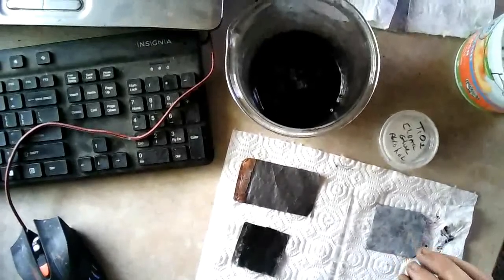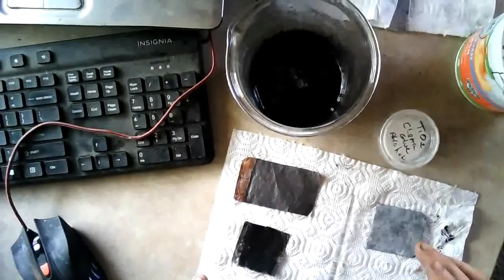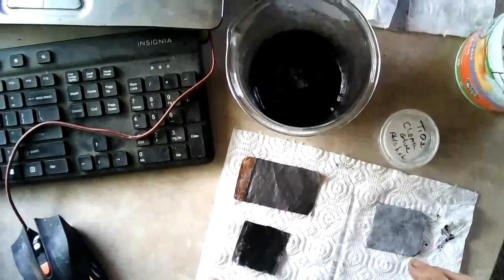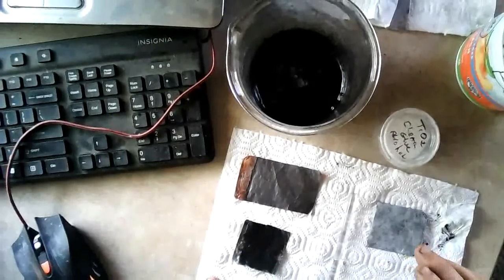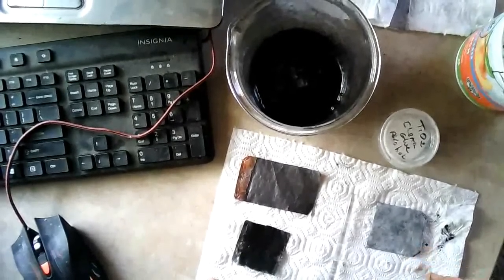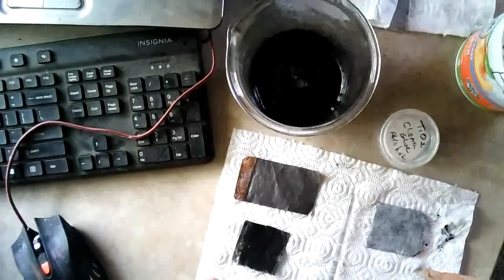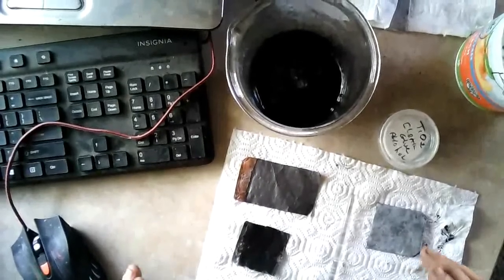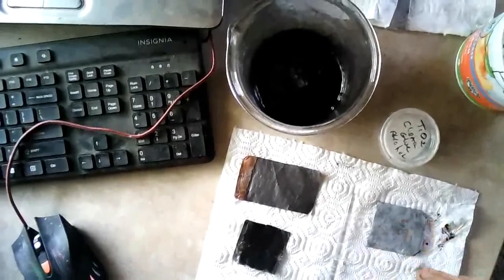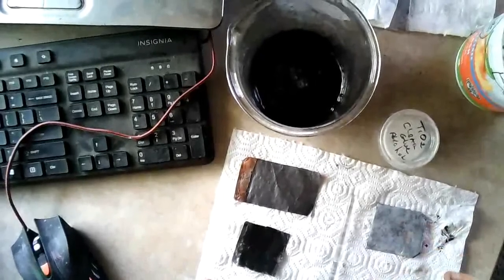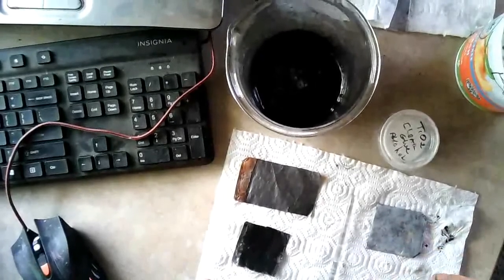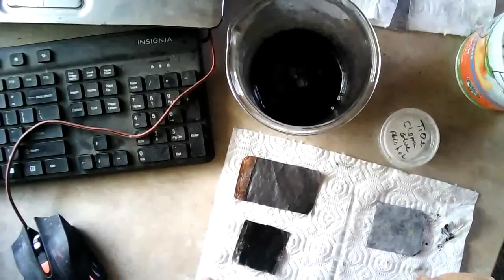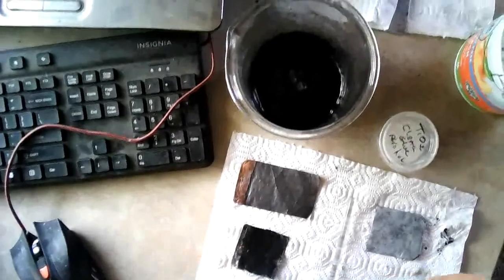If you mix the trisodium phosphate and the borax together and then dip it into it, you get a hard film. You don't really notice it because it's so thin until you go to clean the electrode up, and it was so hard I had to sand it off.